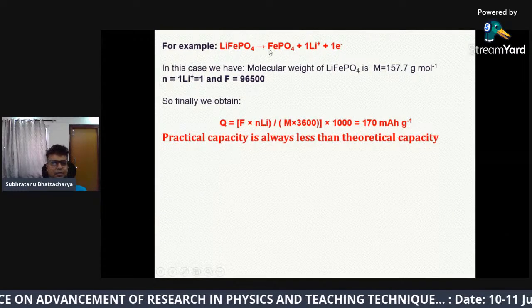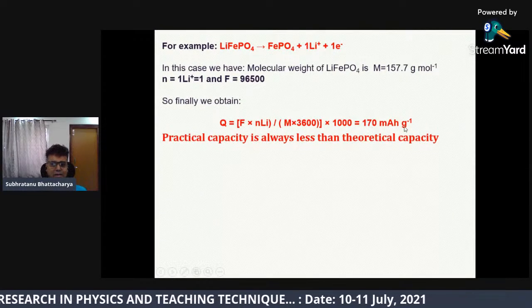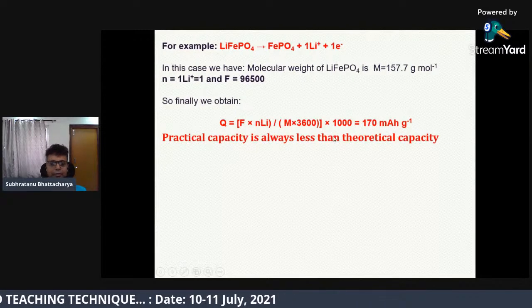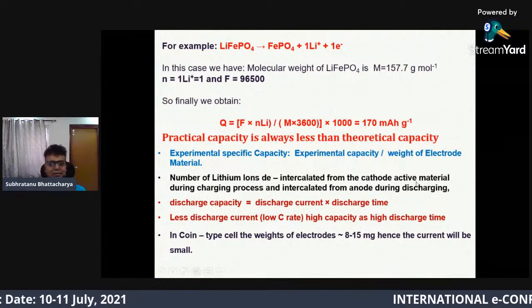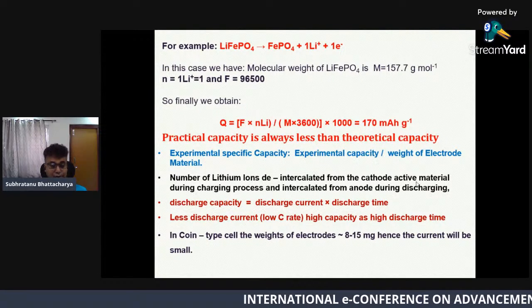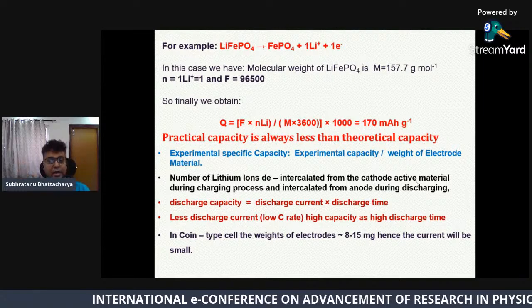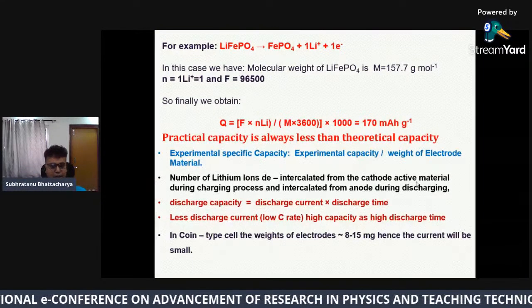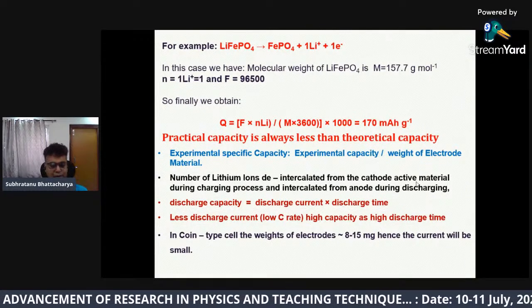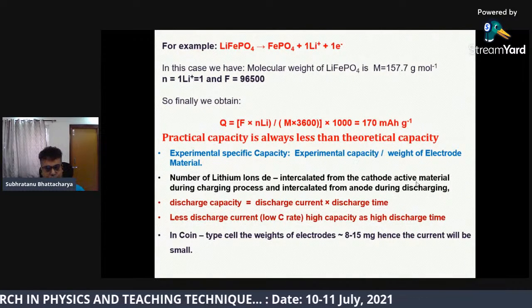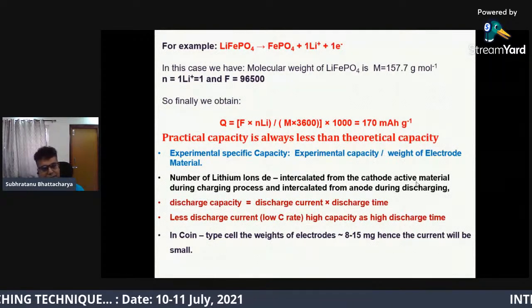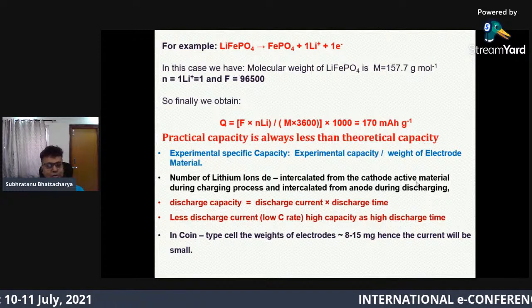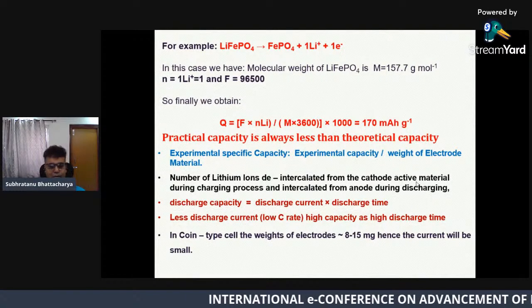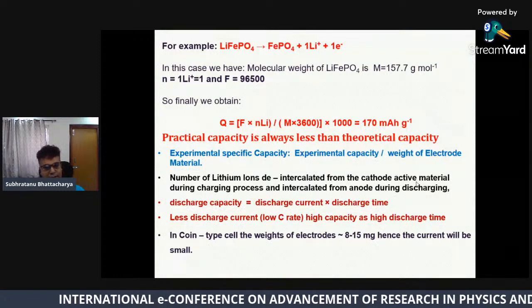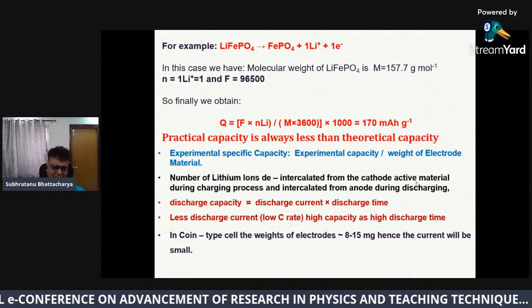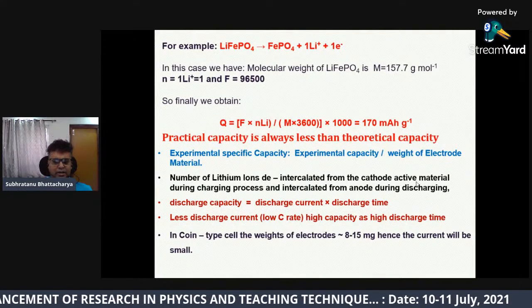With this LiFePO4, you cannot get 170 mAh per gram practically, because there are some issues. You may achieve up to 160 maximum in ideal condition, if you just purchased a battery. But after say 550 discharge cycles, you may achieve only 140, and it will gradually decrease depending upon how you are charging, how you are discharging, how many cycles you have already used up, and something like that. So a lot of issues are there. I am not going into detail on that.